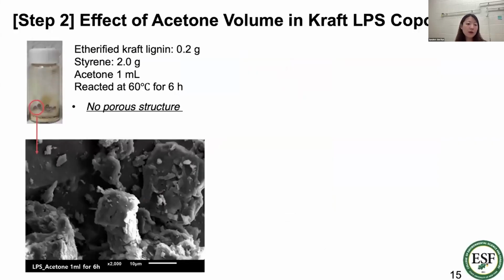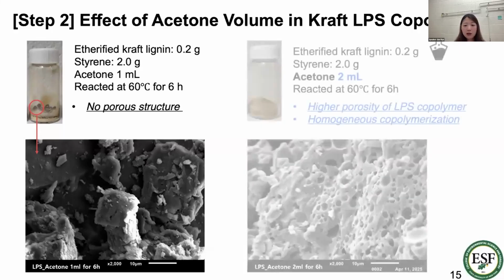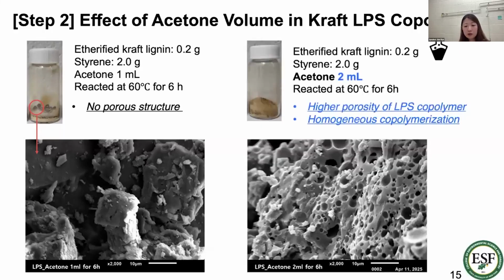So now we have the solvent system for the polymerization, and we observed the structure of the prepared polymer. However, some polymer has a large size distribution, and they have no pore structure when we observed the SEM image. So we added twice the volume of acetone to improve the copolymerization system.